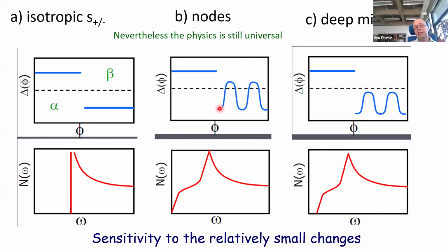It basically depends on the interplay of the order parameters. So you can have a gap which is constant on hole and electron type of Fermi surfaces, roughly a constant but of opposite sign. You can have one being roughly a constant, but another one will have some angular dependence and even cross the Fermi level. So you will have nodal behavior all of a sudden, but these nodes will be accidental. You can even remove them by disorder. Or you can have a situation where the gaps have deep minima and maxima, but no nodes.